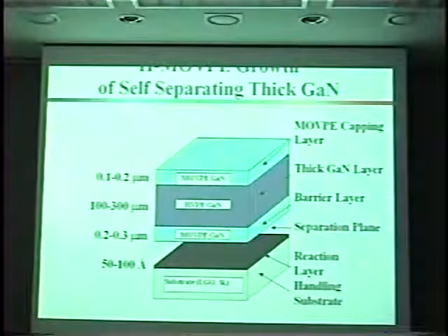The nitrogen terminated surface grows very rough, so we would have to come back and grow a capping layer by MOCVD to revert back to the gallium terminated phase and to grow a nice smooth surface. When we do that, we can produce freestanding gallium nitride. This was produced back in, I think, about 1998 actually. At the time it was the world's largest piece of freestanding gallium nitride, and very high quality. That piece has a full width half maximum of about 47 arc seconds.